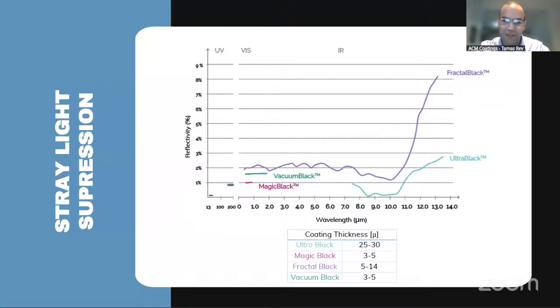So, for example, Magic Black would give you the best optical performance in the visible range, about 1% reflection, and also in deep UV applications. So semiconductor industries and, let's say, space applications, star trackers, they all use Magic Black. If you're looking for something a bit more robust, with more durability in the coating, then we have Vacuum Black, which goes into the near infrared spectra. This coating can really support ultra high vacuum applications, and also applications in the semiconductor industries or where conductivity or tailoring conductivity is essential.